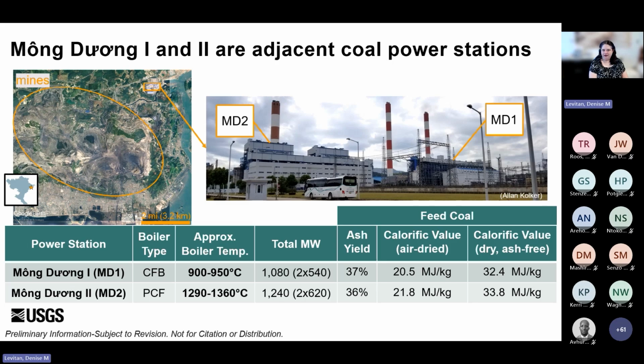And then MD1, the CFB, burns at approximately 900 to 950 degrees Celsius, whereas MD2 is 1290 to 1360 degrees Celsius. And the way that I like to keep track of these going forward and looking at the results is that MD1, lower temperature, lower number; MD2, higher number, higher temperature. So MD1, lower, MD2, higher. Dr. Kolker and his collaborators, when he was there, collected samples of feed coal from the conveyors going into the plants, and then fly ash and bottom ash from each of these two plants. And that's what I'm going to talk about going forward.